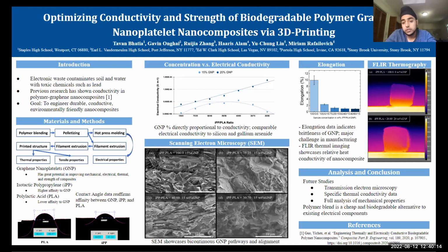We collected relative thermal conductivity data, as you can see by our FLIR thermography section, and the thermal cube was able to allow heat to transfer more evenly throughout it when graphene was introduced. We hope to calculate specific thermal conductivity values in the future. However, when graphene was introduced, efficiency increased, but so did our brittleness. By our elongation graph, you can see that there was a very significant drop-off in elongation when graphene was introduced in the sample, which is going to be a major setback in processing and manufacturing of this blend.